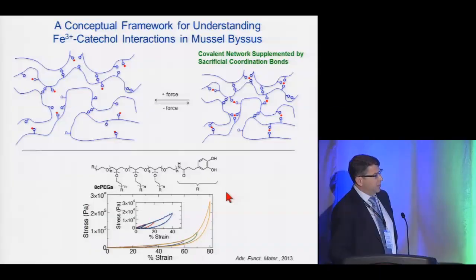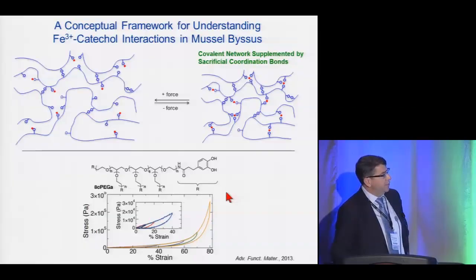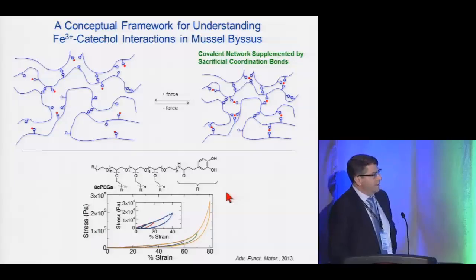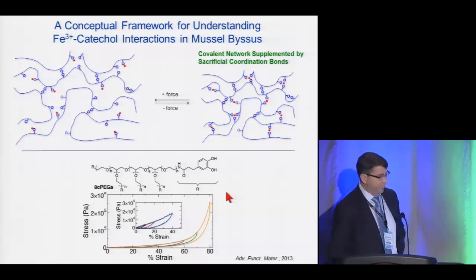This is an 8-arm PEG molecule with the end groups all catechols. We formed a hydrogel by mixing with iron and then equilibrated that gel to marine pH and studied the bulk mechanical properties. And just to make this story very short, the hysteresis you see here between loading and unloading curves is due to the rupture and then reformation of these sacrificial iron catechol coordination bonds, and it actually significantly toughens this material. So this is why we think that these coordination bonds are sacrificial. They dissipate energy when they rupture, and so they toughen the material.